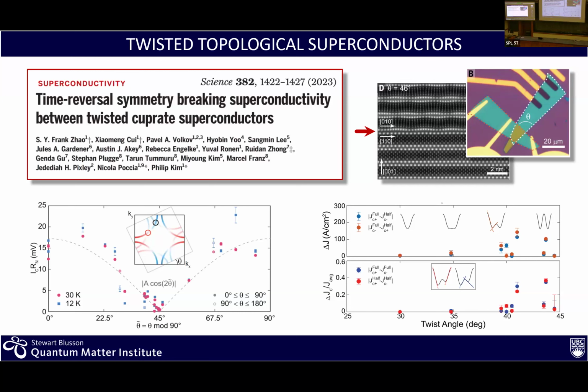And maybe if I can add here for the expert, if you look here, you see this funny modulation. The layers are not flat at the top. And that is because bismuth strontium copper oxide has the bismuth oxygen layer, and bismuth is a big atom, so it gives rise to some mismatch and some modulation along one particular direction. So you can see it in one end or the other, and when you put them together, that certainly can play a role too. It's bringing in a structural asymmetry, which is pre-existing, your pairing, the matching of the superconducting gap. So those details for sure play a role.